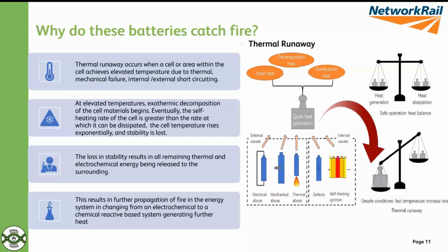As it raises temperature, you get an exothermic decomposition of the cell materials, which then increases the rate of self-heating. And then you reach a stage where the amount of heat being generated is more than the rate of heat that can be dissipated from the battery. And then that results in a loss of stability of the remaining energy within the battery. And then you get this further propagation where you get a release of energy from the battery in a fire.